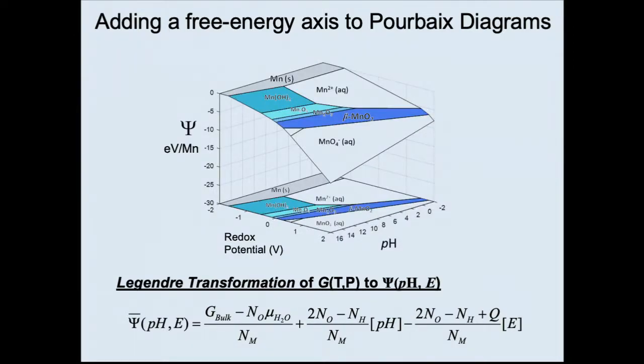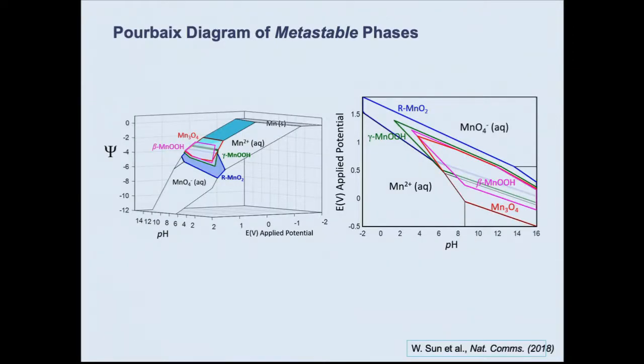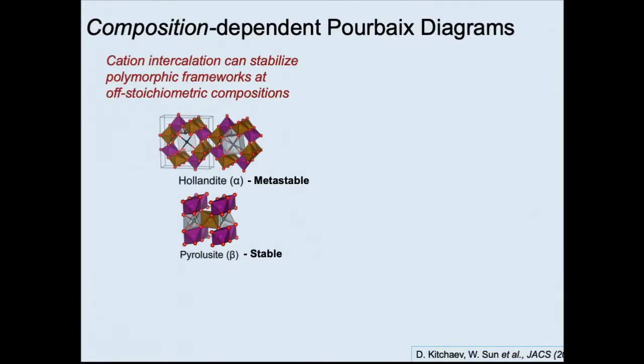And so this is the stable energy surfaces, but you can now put the metastable energy surfaces above there, right? So there are energy surfaces living above the stable convex hull, and you can project this down on the phase diagram. And what you're seeing is that in this region in which I'm playing, the oxyhydroxides are actually very close. So how can I now quantitatively predict the reaction sequence?